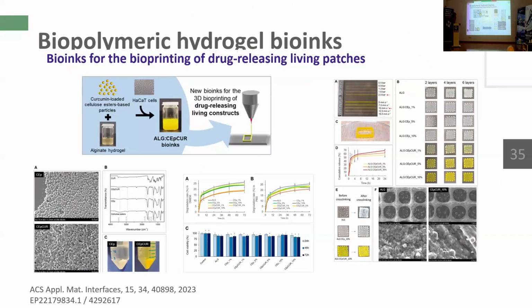We are not only using nanofibrillated cellulose. In this study, it was a completely different concept, and I really enjoyed this work. This work intended not only to use cellulose structures to reinforce the inks, but also to incorporate other properties. And we achieved this by using cellulose-based particles that were loaded with a model drug, a model compound, and then these particles were incorporated into the ink formulation. And this allowed us to produce a 3D construct that, apart from being a living construct with cells, also has the ability to release a drug.